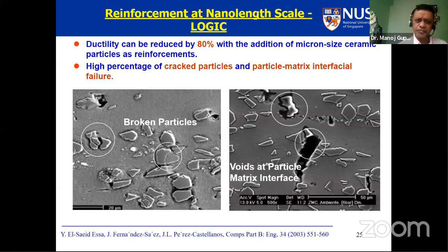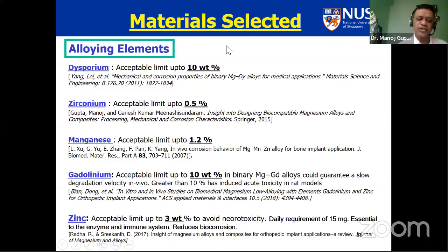When we use nanoparticles or particles in the nano length scale, it avoids two things. The picture on the left hand side shows particles breaking. This happens when you have micron size particles and higher, or they debond. Once these two damage mechanisms come in, you do not realize the strength, ductility, and toughness of the material. The ductility can be compromised by almost 80%, which is not good news. So essentially that is the main rationale of using the nano reinforcement.